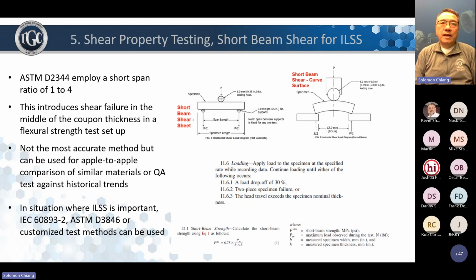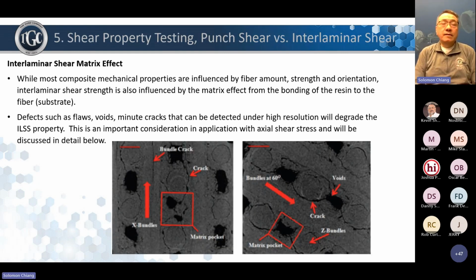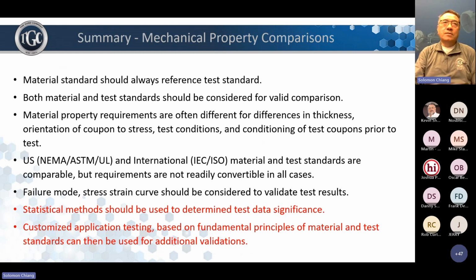If you want to compare A to B for screening tests, and you don't want to go into the more elaborate ILSS, then you can use the 3-point bending. One reason ILSS is the weakest part of a thermoset composite is because it is influenced by the bonding of the resin to the fiber. So if the fiber has void and porosity in it, then you can see that it will be weak on the ILSS.